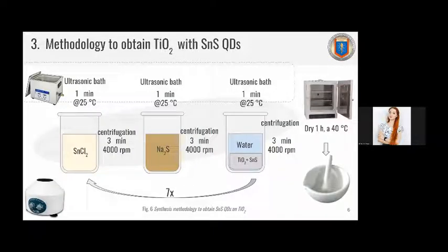This is the process of what was done. The synthesis methodology to obtain the quantum dot tin sulfide on titanium dioxide was the following. We had the anatase phase of titanium dioxide that was added to tin chloride, which was dissolved in distilled water, and underwent an ultrasonic bath at room temperature for 1 to 2 minutes. Then the solid and the liquid parts were separated through a centrifugation process. The solid part, which contained the titanium dioxide, was collected, and the liquid part was removed.